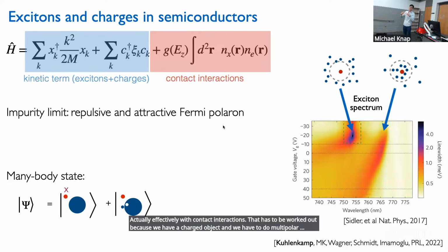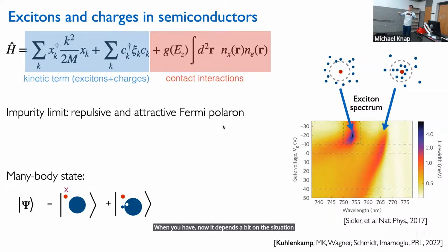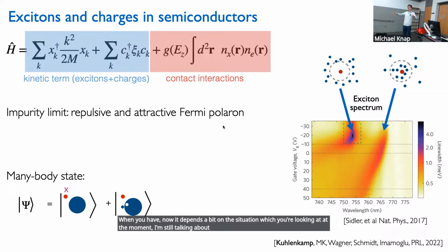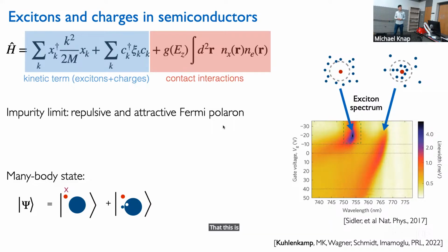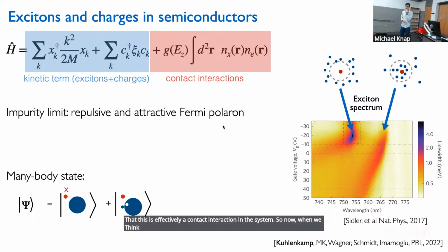Now it depends a bit on the situation which you're looking at. At the moment, I'm still talking about a single layer. When you have an exciton there, and a charge, then the effective interactions would be 1 over r to the 4 when you do a multipolar expansion. But it turns out that in 2 dimensions, one can show that this is effectively a contact interaction in the system. So now, when we think about this effective Hamiltonian, what do we have? So now we have a Fermi sea of electrons. We have impurities immersed into this, we have excitons immersed into this Fermi sea, and they are interacting with respect to each other with some contact interactions.